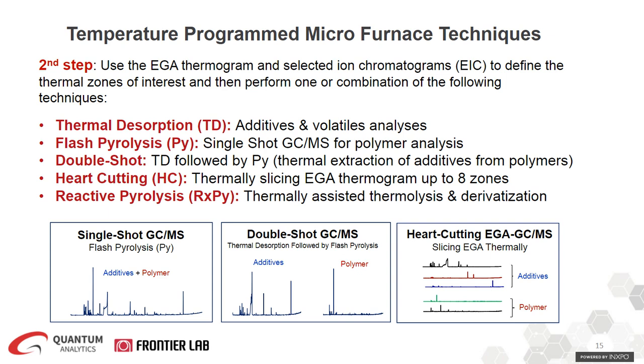We call flash pyrolysis a single-shot GCMS as well, and that's been shown on the left-hand side at the bottom. So in a flash pyrolysis, that is a fundamental technique for analyzing your polymers. Most of the time, temperature, say like 600 or 700 C, to break down your polymer or the heavier components. Then you will obtain a GCMS chromatogram. So you're performing one or single analysis on your sample. And that chromatogram that you will obtain is the combination of additives, lighters, and the polymers.